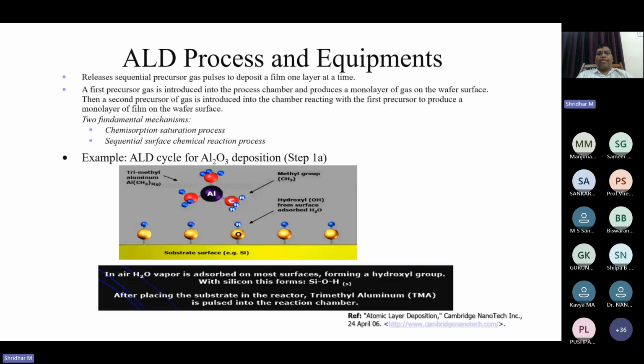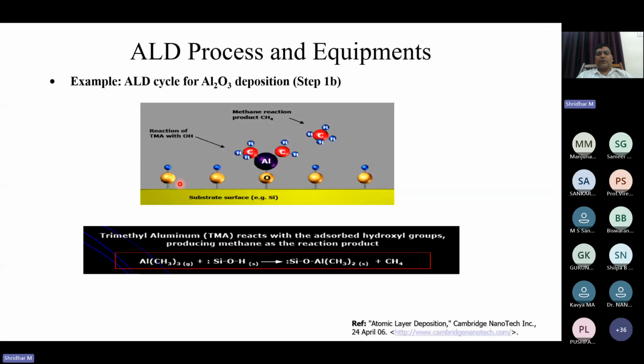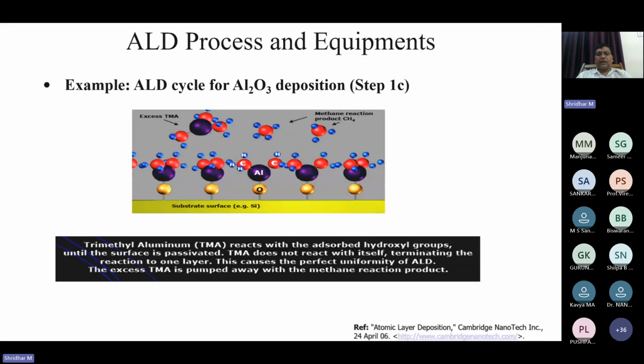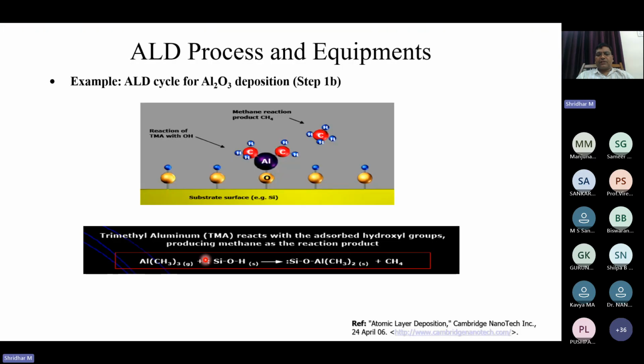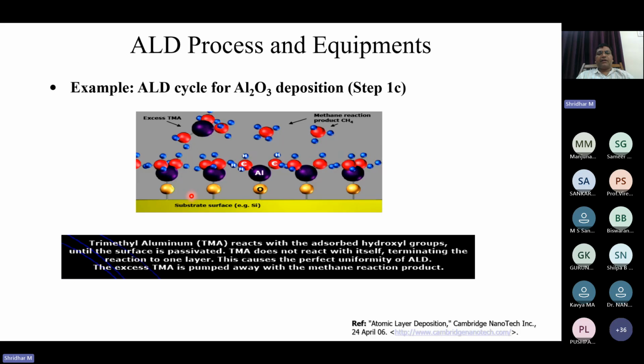What happens next? They will react and they will come and sit on this silicon oxide. It is actually Si and O2, so oxygen will be there. Oxygen will be attracted by this aluminum, and Al2O3 will be formed on this silicon. You can see this is the chemical reaction, and finally we will be having Si-Al2O3. Yeah. And here the extra material will be taken out. Here this material wanted to sit on this, but there is no oxygen to hold this extra molecule. So that is why a single layer of Al2O3 deposition is possible on this surface using this ALD process.